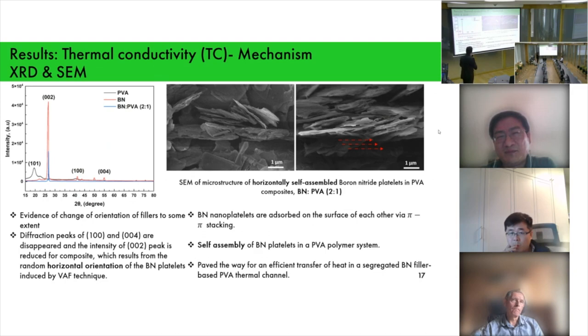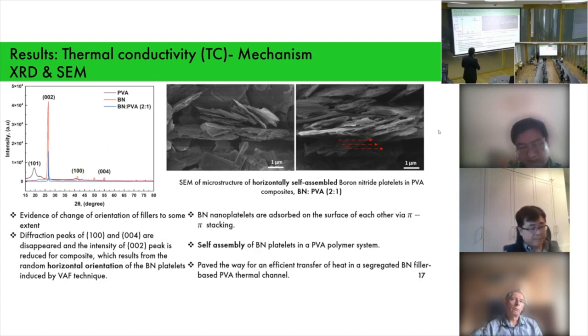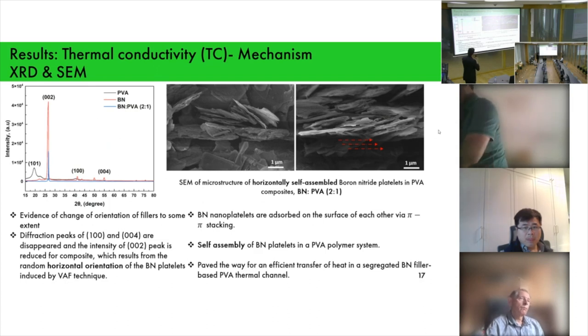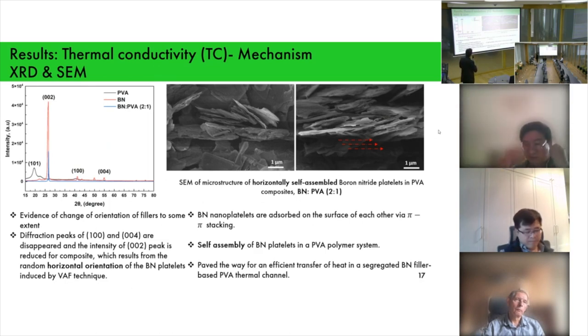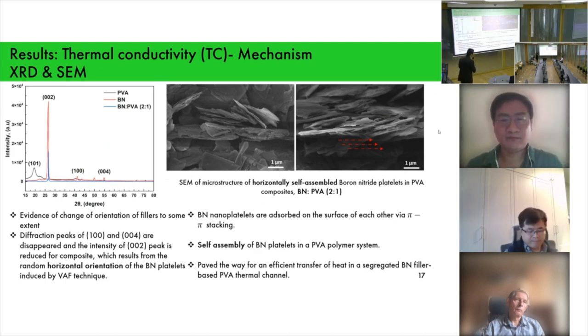But I was reading the literature, and they say that if you have this peak enhancement or degradation, you see that the orientation of the platelet, because here you see that these diffraction peaks depict the orientation of your platelet in a certain direction. So when they disappear and the intensity is high, then you see that there is a slight shifting, a slight change in orientation compared to the pure material. So we feel that there is horizontal orientation of these BN platelets, which supports the mechanism that we involved in the SEM analysis.